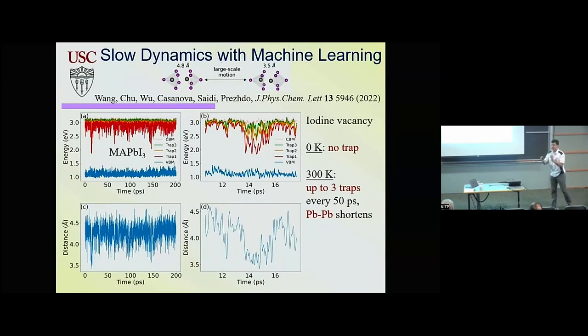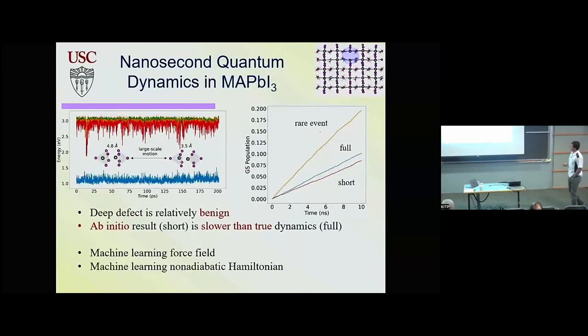Again, we developed a machine learning force field. What we see is that there's a very slow acoustic mode with a period of 50 picoseconds, very low frequency. This mode brings those two leads together. When they come together, they make a lead dimer, and they create many states, up to 3 mid-gap states that show up in the gap. But luckily, this happens transiently, so even though you have a trap state that's 1 eV deep, it does not influence the performance.